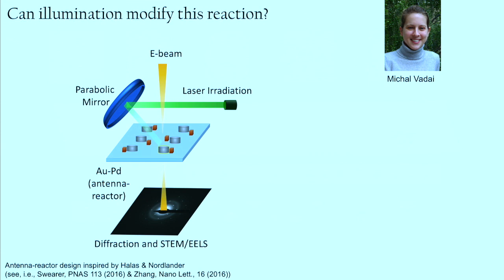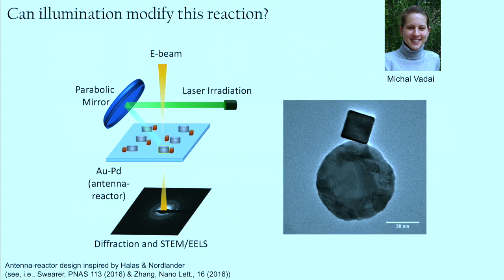Like I said, we have the setup where we surround our sample by two parabolic mirrors. We're going to use the same palladium nanoparticle system, except that palladium on its own isn't a particularly good light absorber at optical frequency, so we decorate it with gold nanodisks to enhance the amount of light that it's absorbing. So here's an antenna-reactor pair.